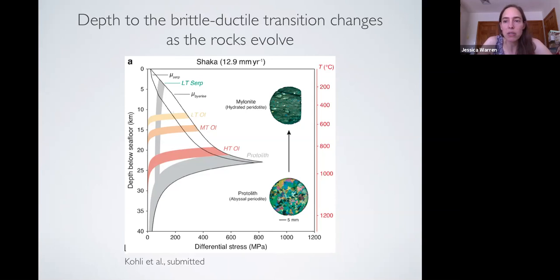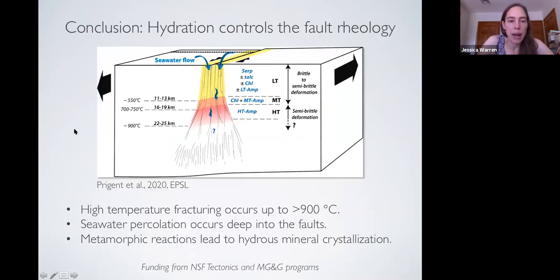But that grain size reduction really seems to be linked to the formation of the hydrous phases and the metamorphic reactions going on in the rock. And so this is my last slide now. So this is our conclusion, which is that hydration is controlling the fault rheology, is leading to nucleation of new phases, but it also seems to be driving the grain size reduction process in these rocks.